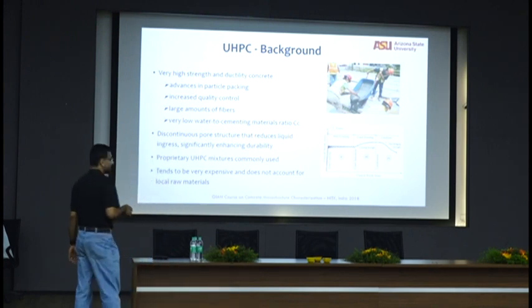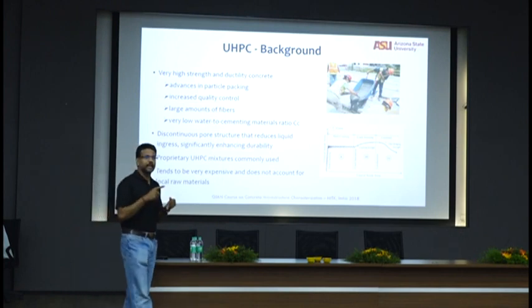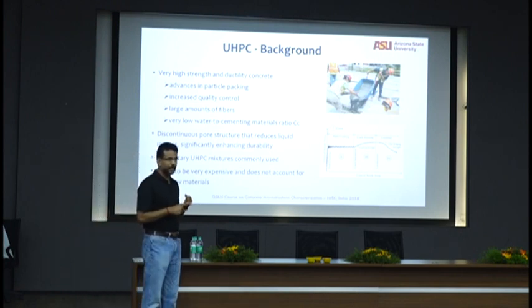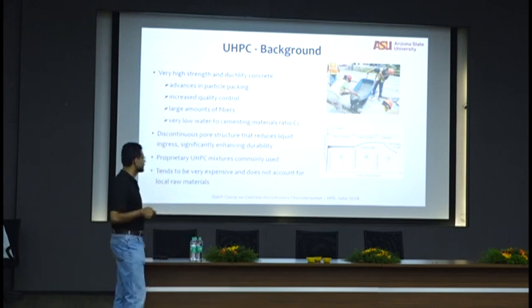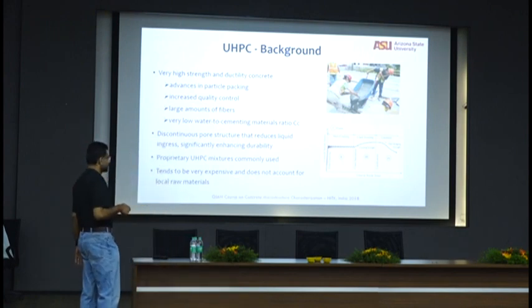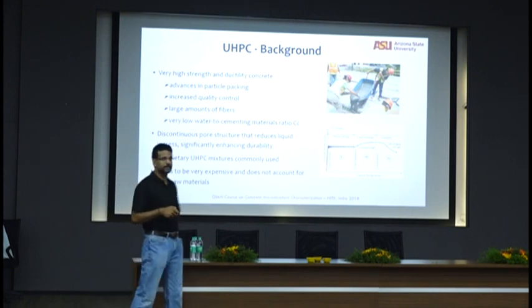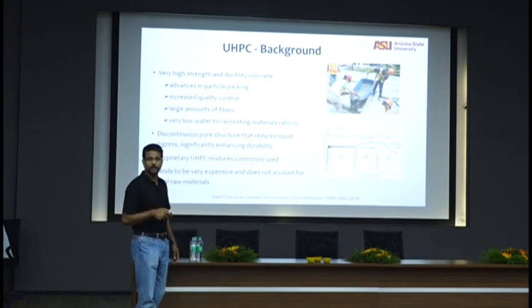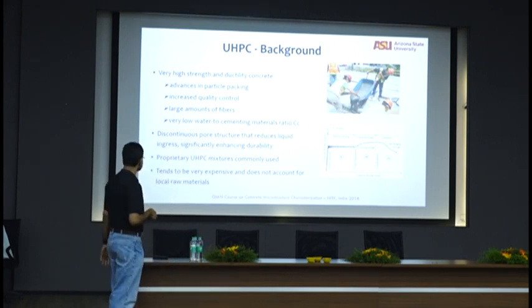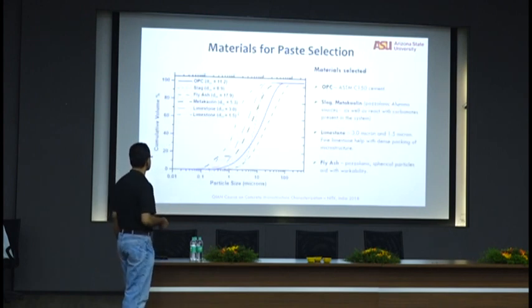So you need very good quality control, extremely good quality control in selection of materials, in mixing. It requires really long mixing time, very high dosage of superplasticizers, very low water cement materials ratio. So whatever I'm going to talk about is about 0.18. Water cement ratio of 0.18. Tends to be proprietary mixes, tends to be very expensive, so we need an alternate solution.